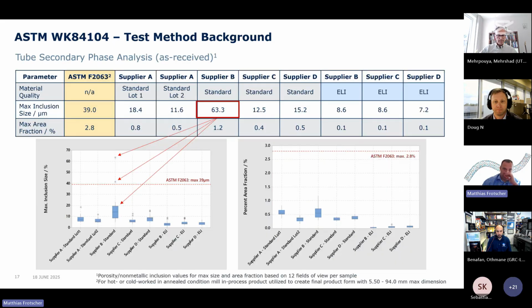So, moving on to the results, the following slide represents a supplier material evaluation showing the usefulness of the inclusion test method in determining equivalence between materials. Keep in mind that depending on the sample geometry, the results will not just be a question of material purity, but also of the sophistication of the manufacturing processes being applied. So as an example, supplier A could use a standard nitinol quality and produce a premium quality tubing with superior tube manufacturing, whereas supplier B, who has access to a high purity ingot material but has less sophisticated tube manufacturing, may result in an inferior fatigue performance of a device made from the latter tubing. So in order to manufacture a superb tubing, you have to master both the material quality and the tube manufacturing processes. And there is a huge variability out there on the market for both of those.